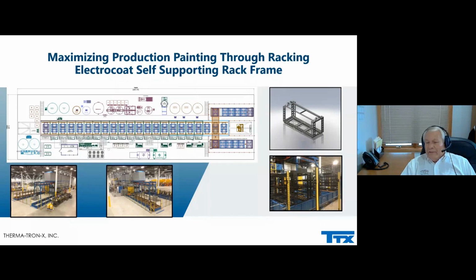It could be delivered by an AGV or a forklift driver with an accumulating roller conveyor or chain conveyor that allows accumulation of 30 minutes or 40 minutes, depending on the lunch break. And it continuously can feed a square transfer system through the process, unload it automatically, and accumulate those for the AGV or a forklift to pick it up. Here you see a typical style of that, but it's very big now in the automotive areas because more investment capital is being implemented to minimize the amount of labor costs. So the configuration of the racks that you see here, going in, coming out, and going out for either forklift pickup or an AGV. And here you see them accumulating.